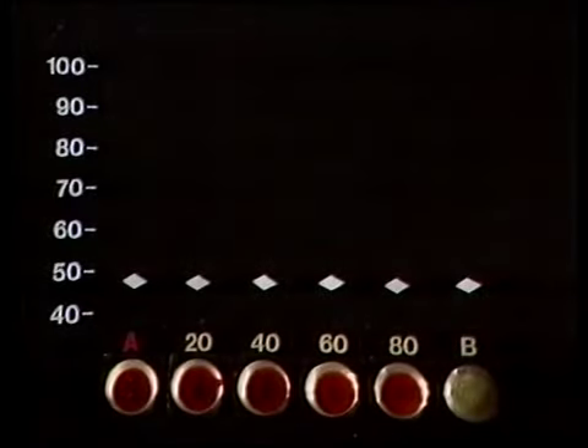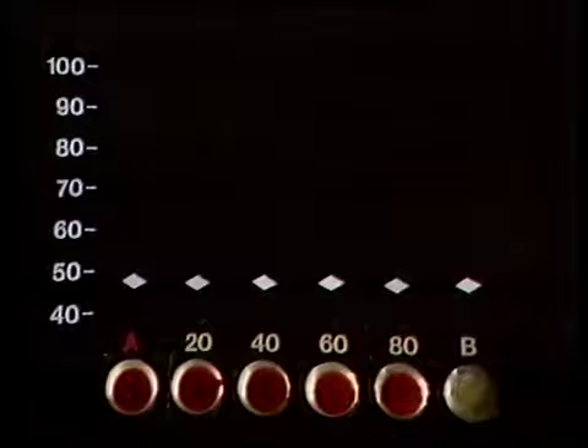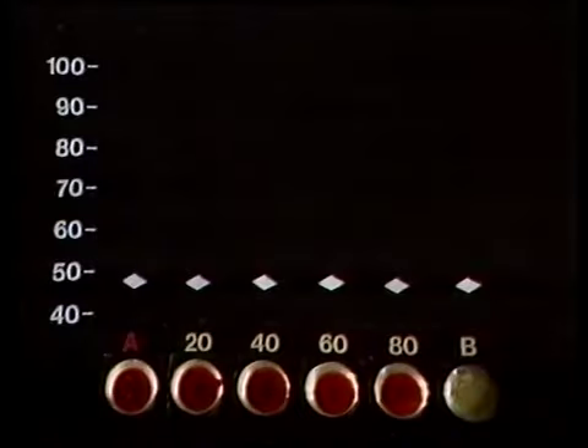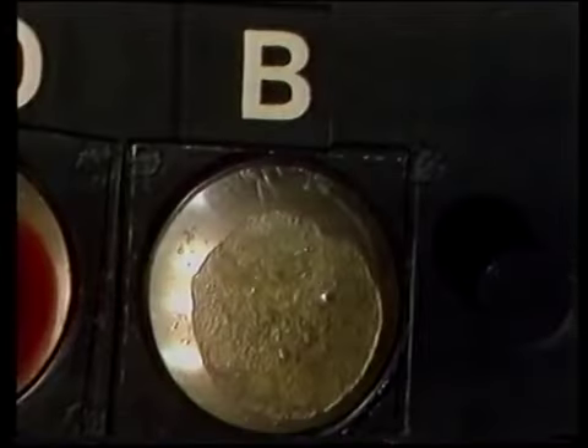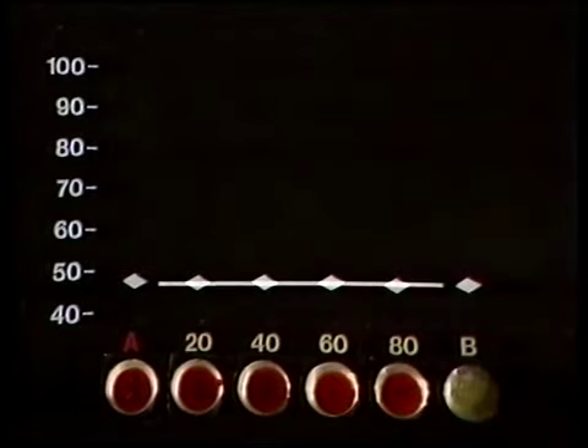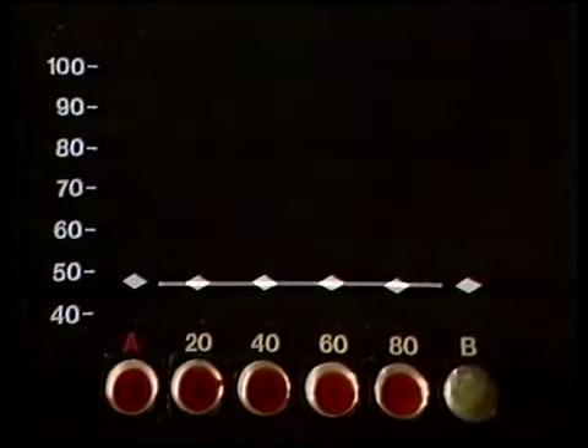Well, we're at 46 degrees centigrade. That's the temperature of the eutectic. And there's some liquid in the 40% B dish. In fact, there's some liquid in all the dishes that have got mixtures of A and B. At this temperature, only the pure A and B samples are still completely solid. So all the mixtures begin to melt at the eutectic temperature.